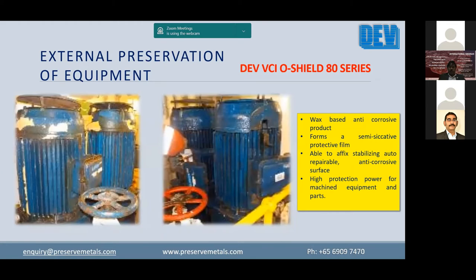This Echo Glossy will be an ideal solution. Now coming to the external preservation of the equipment, on the bare metal parts, VCI O-Shield 80 series is recommended because it forms a wax-based anti-corrosion coating. The advantage is that the base metal, like the motor shafts or the pump shafts, or any bare material, remains visible. But because it is a wax-based coating, this can even be subjected to outdoor conditions of rain and shine.